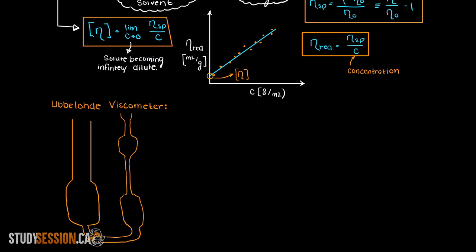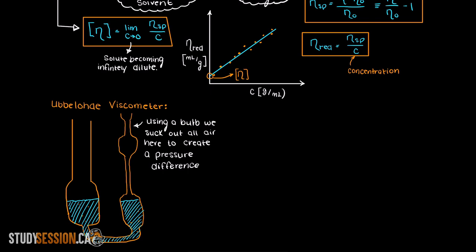We place a solvent of known properties into the base of the viscometer, then add a known amount of solute. And then we create a vacuum on one side of the viscometer. This pressure difference between the left and right side of the u-tube will force the liquid up the right side. From this, the time can be taken for how long it takes the fluid to climb the capillary, which is just another way of saying a very small hole.